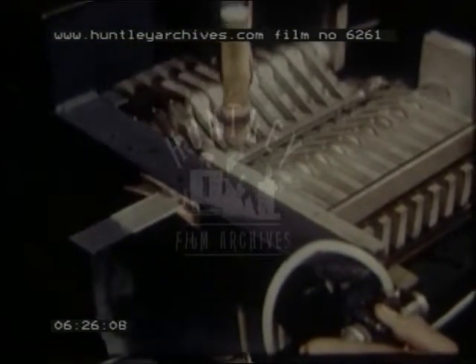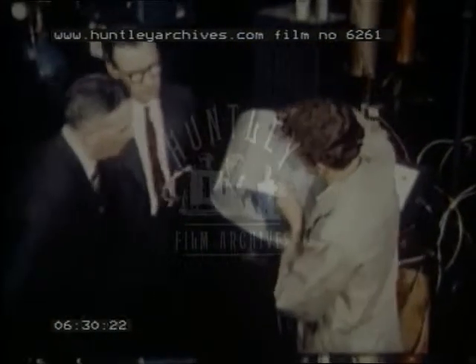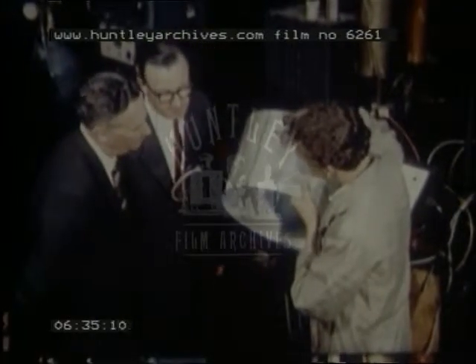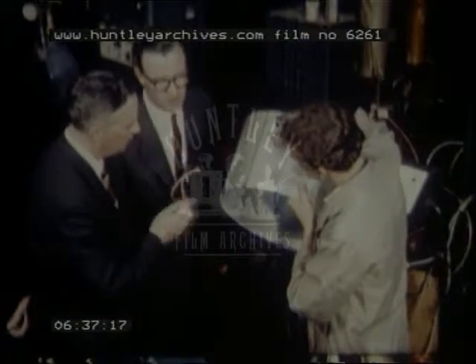Care in jigging is of paramount importance, as the edges must butt together perfectly. It is for this reason that a prior blanking operation, as you have seen, is introduced. Should there be any misalignment of the edges, this is the type of weld defect that can occur.